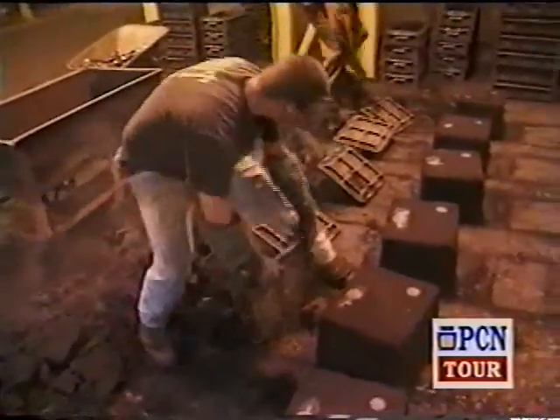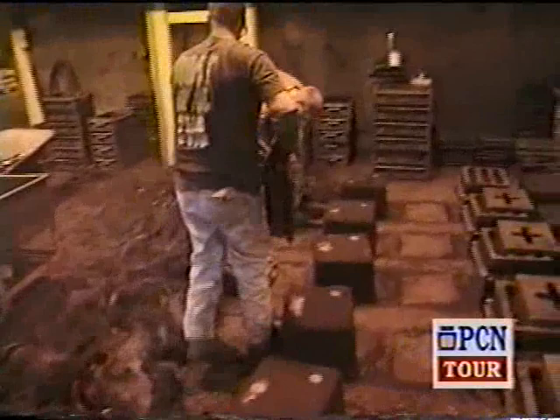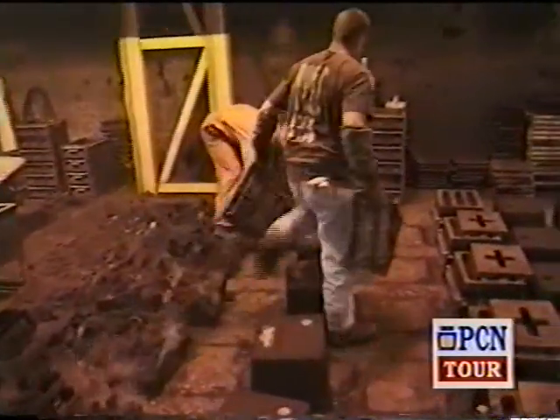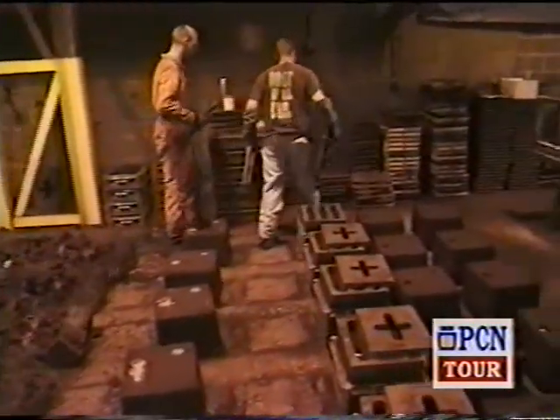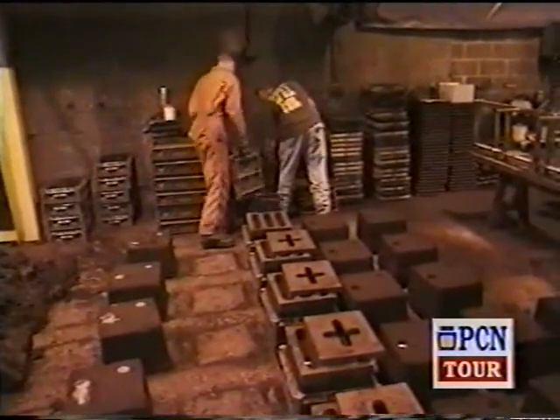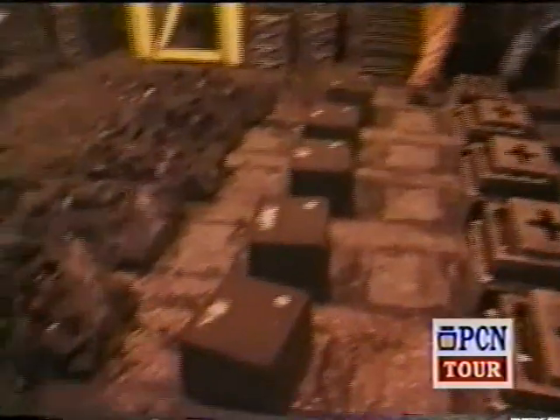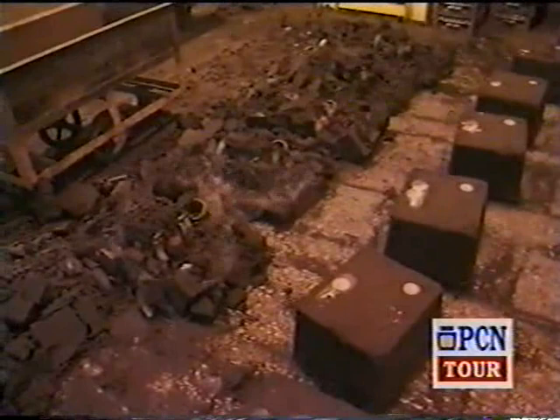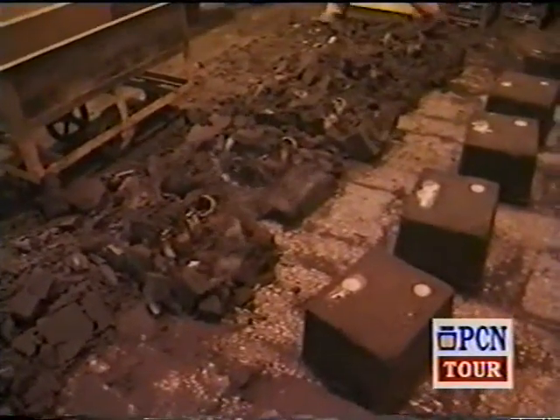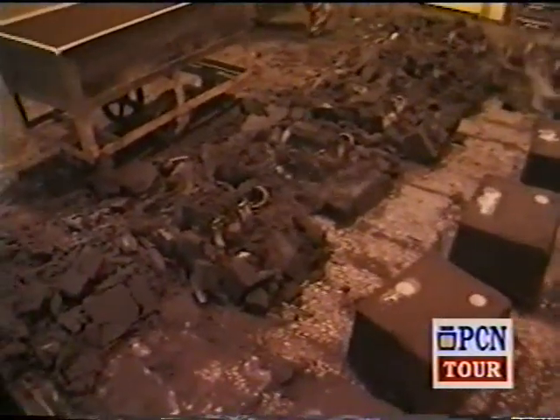After they've sat for roughly 15 minutes, the molds are dumped over and your casting comes out. This is a very critical point of the casting because if they don't sit long enough and they're dumped, you get hard spots in the castings and then you cannot machine them. So this is a very critical point of making the casting, so that you don't get hard spots.